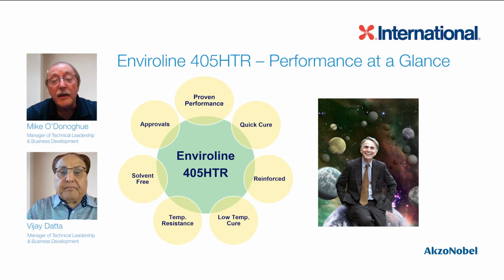One of the great beauties of that particular lining, VJ, is its large temperature resistance. We've obviously used it up to 300 degrees Fahrenheit, and we've actually tested way beyond that too. One of the real delights is that it's solvent-free. And as long as we're applying it properly with the hydrocats, etc., we get fabulous wetting out of the surface. As a result, with the good success we're enjoying, approvals abound with the oil majors.